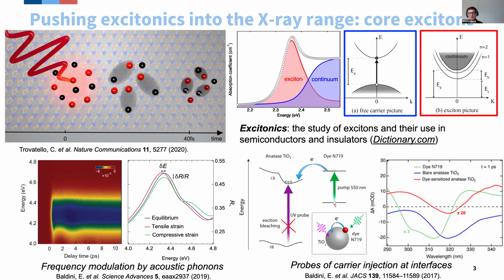This is an experiment where a photon is absorbed by a dye molecule that's attached to the surface of an electron acceptor, in this case, titanium dioxide. When the photon is absorbed, the dye molecule goes to an excited state. And in this excited state, the electron now has sufficient energy to be injected into the conduction band of titanium dioxide. And when it does so, these new electrons in titanium dioxide will actually affect excitonic resonances.